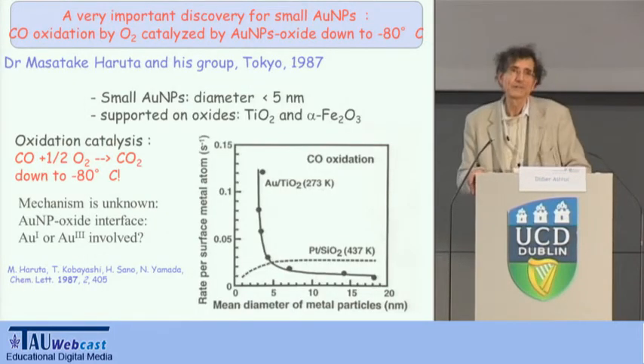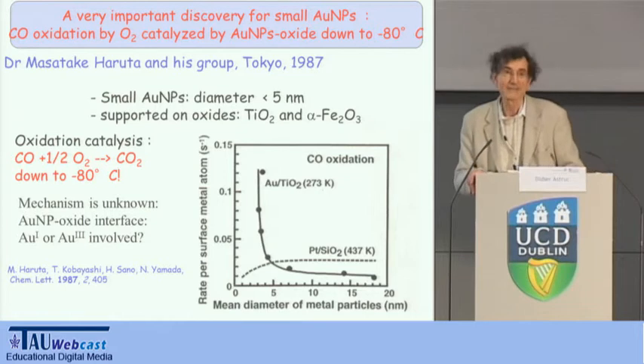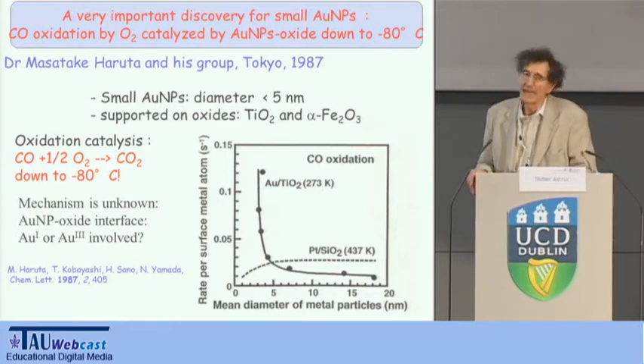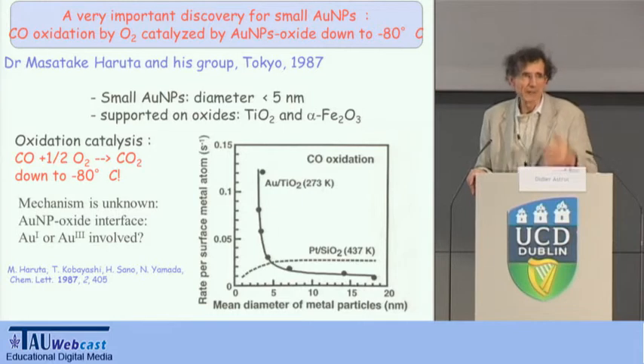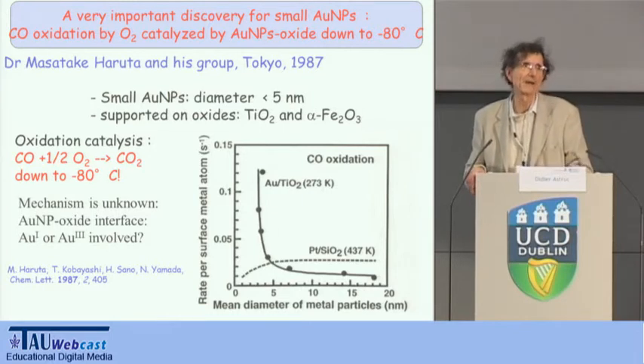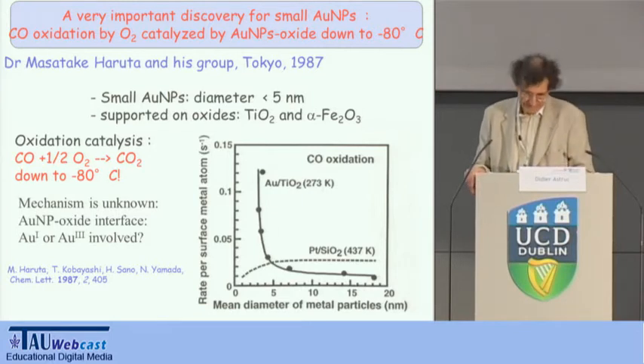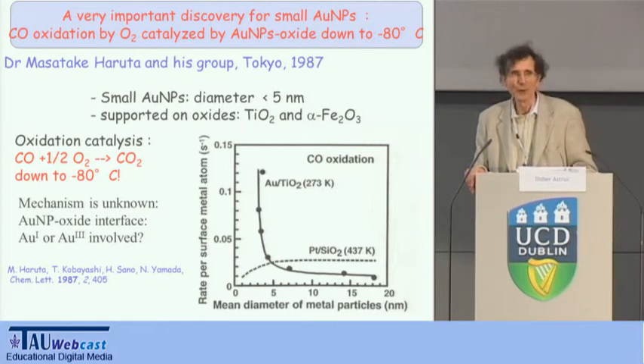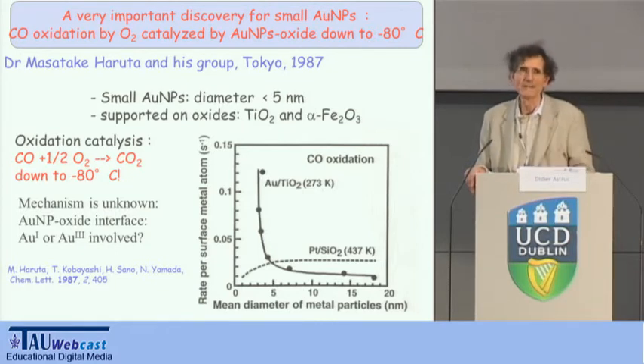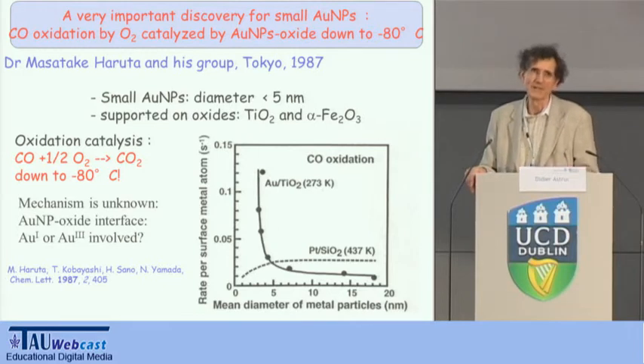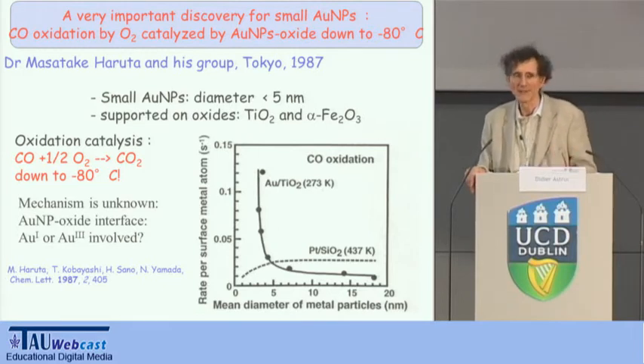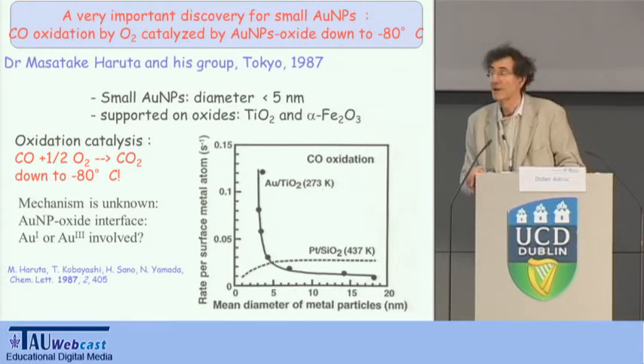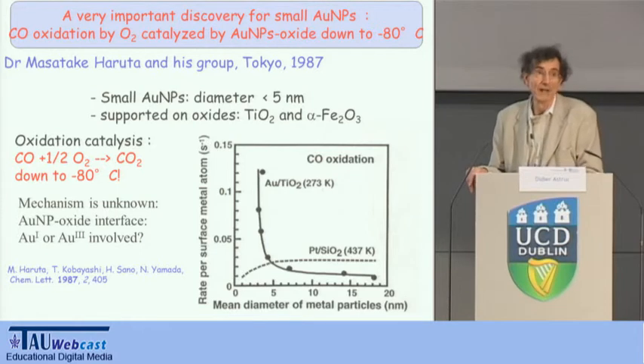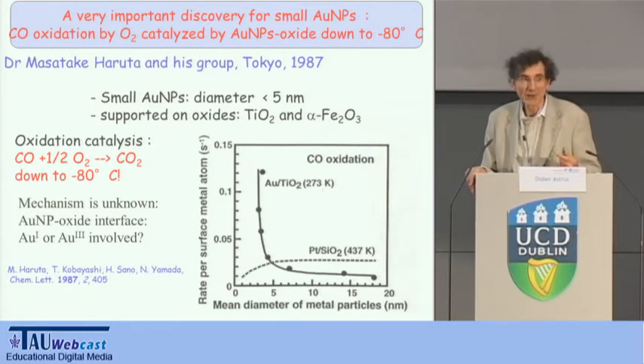One last thing I would like to say about gold nanoparticles is catalysis. In the late 80s, the discovery by Masatake Haruta in Japan was very important when he found that gold nanoparticles coated with some oxide, which can be a transition metal oxide or main group oxide, are able to be a very good catalyst, even at minus 80 degrees, which shows that gold can be extremely reactive when it is in the shape of small nanoparticles.